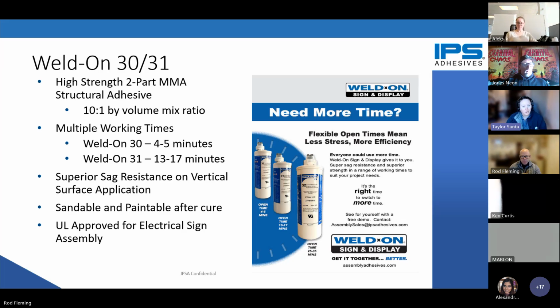You can use the Weld-On 30, which is a 4 to 5 minute product. And then if you do have larger parts, larger signs that you are building, the Weld-On 31 is better because you are having a 13 to 17 minute window to actually get the adhesive down, parts together in the right place and cleaned up before the reaction starts happening and the adhesive starts curing.